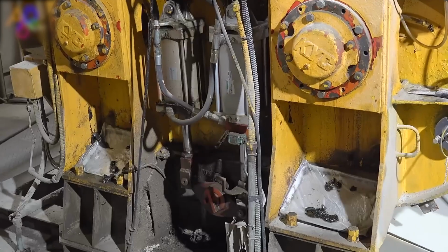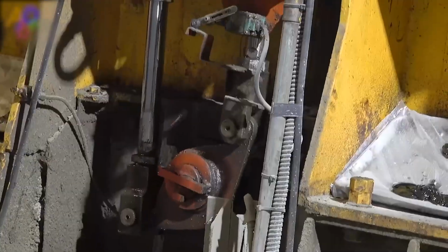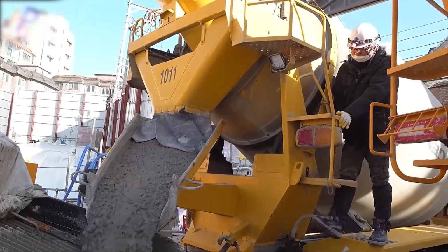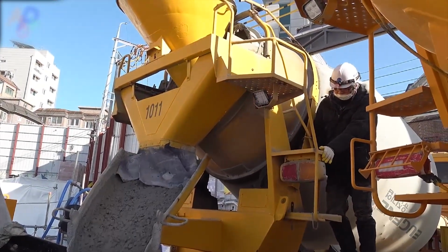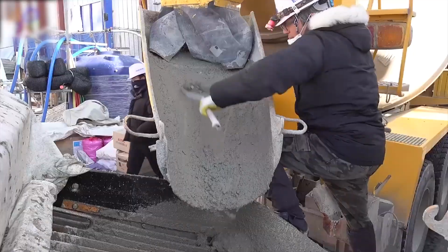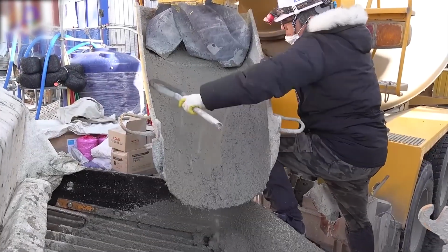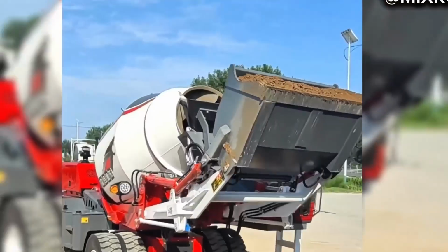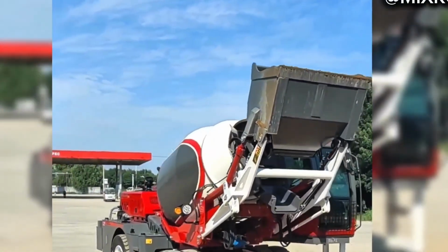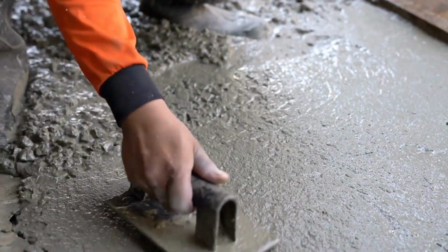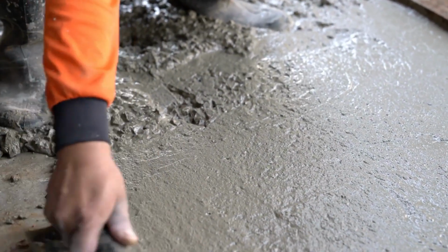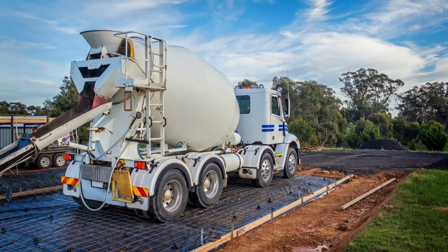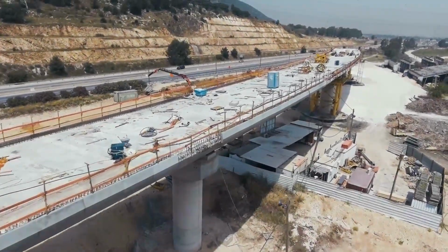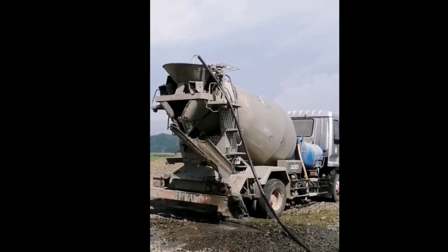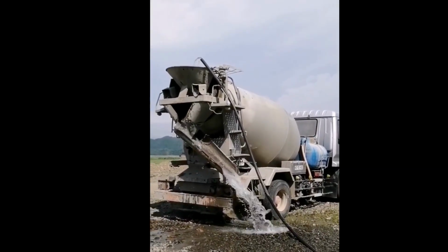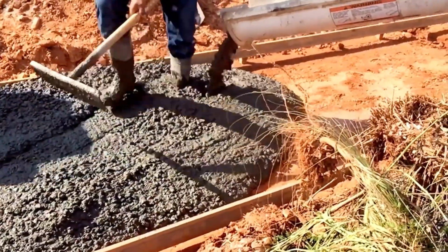This is one of the least talked about components on a concrete mixer, and one of the most important. Every revolution of the drum is recorded from the moment mixing water is introduced at the plant. The counter is mechanical, bolted to the drive system, and visible to the driver. Once the drum crosses 300 revolutions, the concrete is considered potentially compromised. It may have lost workability, begun early strength development, or undergone excessive air loss. The driver cannot legally pour it. Depending on the situation, the load either goes back to the plant or is dumped.